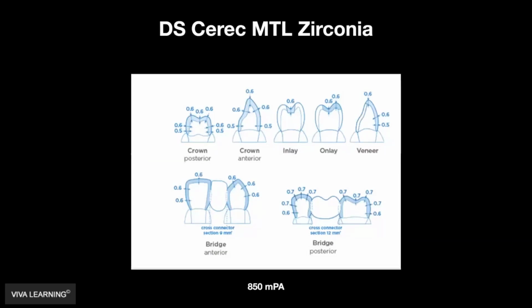Now, this is another material that's out there. It is distributed by Dentsply Sirona. It's actually manufactured by Vita, the CEREC MTL. Again, a great strength. We're talking about getting down into 0.6, 0.5 millimeters of reduction. But again, you're looking at 850 megapascals. So not as strong, kind of somewhere in the middle of what we just talked about. But another great material that has transitional layers, multiple translucency layers, and you have more incisal translucency with more chroma. I couldn't figure out what type of zirconia this is. Maybe they have their own secret sauce like Katana does.